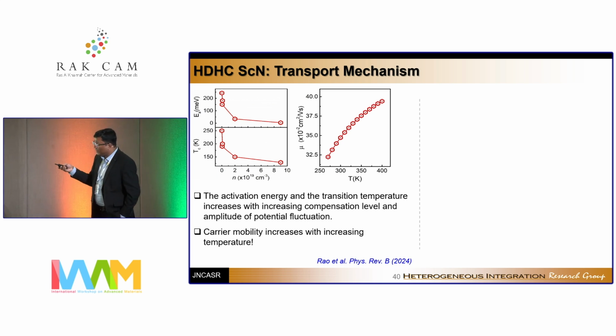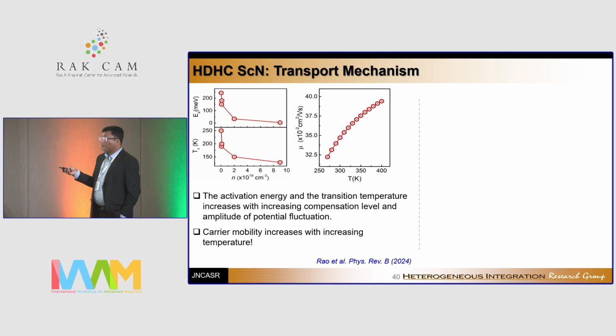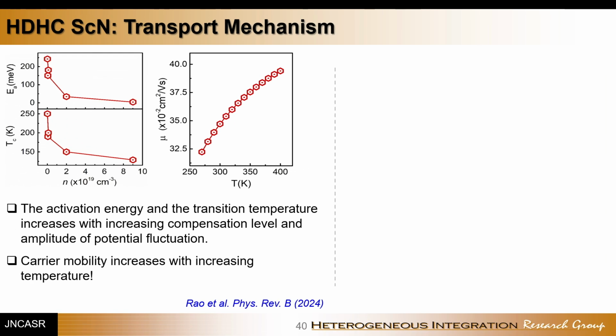Interestingly, as you can see, the mobility in this particular case actually increases with temperature. Mobility for most materials should decrease with temperature, but in this particular case, because it is a potential fluctuated semiconductor, the mobility increases with temperature.